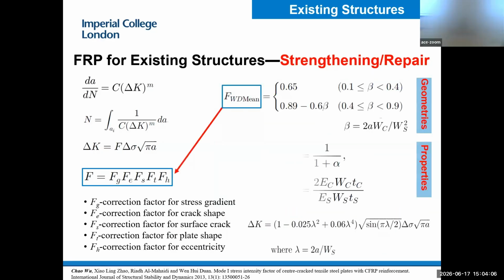So far, we have introduced two modification factors. One considers the stiffness, the material properties of CFRP. The second considers the geometry of the material. Then we can introduce these two modification factors into the Paris law, meaning that in the future, when you design steel structures strengthened by FRP, you can continue using the current available steel design standards. The stress intensity factor is available there, and you only need two additional modification factors for CFRP. That's easier for civil engineers to design the structure.